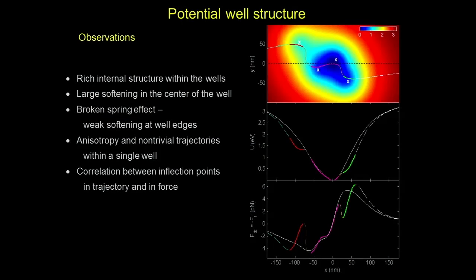If I plot the energy here — these are unstable points — but this is well number two that we try to mimic. It actually looks like these satellite wells break the spring. The vortex feels this sort of interaction because it averages over the core, and pins are always separated by about xi. By just putting a random distribution of potentials, each pin's action will auto-assemble into stronger pins that are each about xi apart from each other, and the fact that some of them are slightly closer than xi gives rise to this rich dynamic we observe.